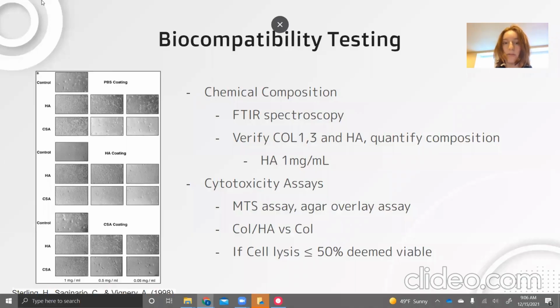For our biocompatibility testing, we would first verify the chemical composition using Fourier transform infrared spectroscopy. We would verify that there's the presence of collagen 1, 3, and hyaluronic acid, and then we would quantify the further composition, verifying specifically that the hyaluronic acid is 1 milligram per milliliter. We would also perform cytotoxicity assays, specifically MTS assays and agar overlay assays, looking at the collagen and hyaluronic acid scaffold versus just the collagen without the hyaluronic acid.